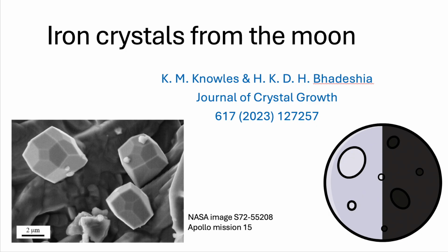So the trace impurities in the vapor act as a kind of filter, forcing the crystal into this unusual shape. Precisely. The source material actually draws a parallel here to studies on other materials, like iridium. They've shown that faceting on high-index surfaces, like iridium {210}, can be entirely driven by these chemical effects, by absorbents sticking at the nanometer level. So these trace vapors in the lunar environment, whatever they were, acted as a kinetic filter. They drove the pure iron to crystallize in this high-index, energetic, and really quite beautiful form. Yes. That complex geometry is literally an indelible record etched in iron, a record of the vapor chemistry that surrounded it billions of years ago or whenever it formed.